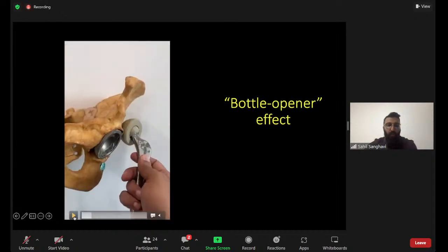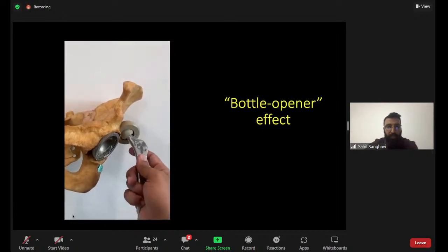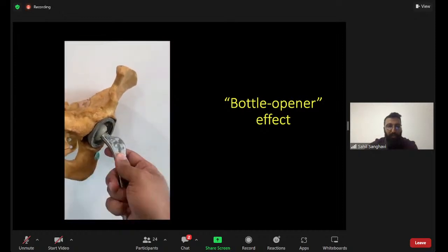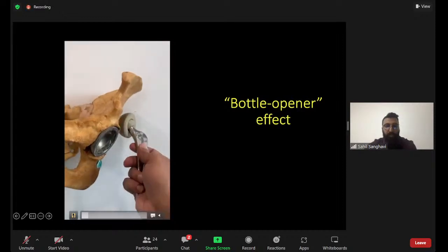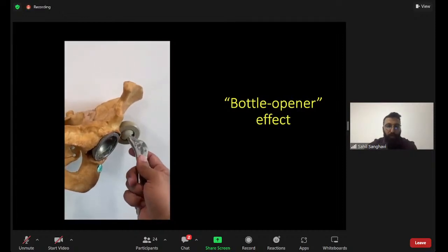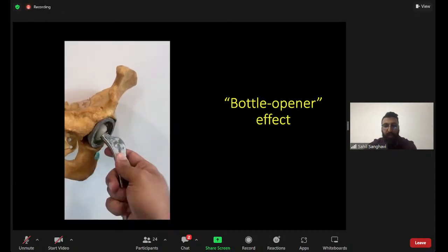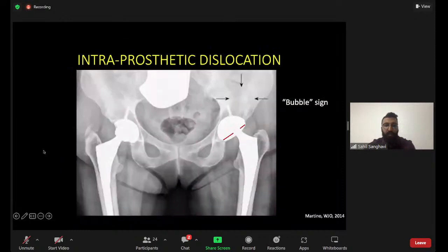What happens is, when the dual mobility implant has dislocated, so for the sake of demonstration here, I've taken a bipolar head and just put in an old acetabular shell in the pelvis. Now, when you have a dislocation of dual mobility and you are performing a closed reduction, as the head impinges on the rim of the acetabulum, what happens is the polyethylene gets dislodged and only the head will go and get seated inside the acetabulum. So this is known as the bottle opener effect. Like you're opening a bottle, the cap of the polyethylene goes out and the head gets lodged again into the shell.